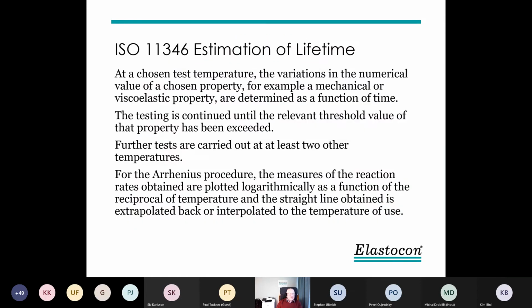Now we come into how we estimate the lifetime. This is a picture which has too many characters, but I took the copy of the standard to explain what we are doing when we estimate lifetime. At the chosen test temperature, the variations in the value of a chosen property, and this property we have chosen is the counterforce. You can do this type of evaluation and do the elongation at break, or compression set, another property, which is important for the function of the product you want to use the material. And we determine this value as a function of time.